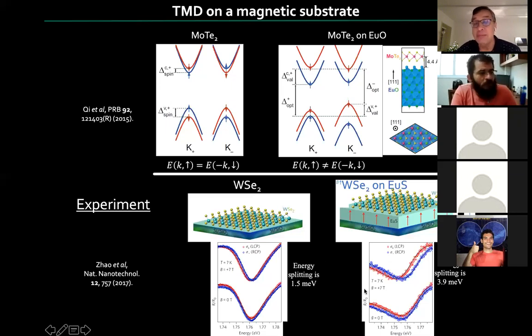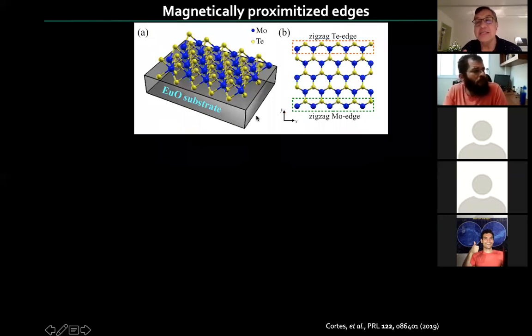And people have actually measured that, because you can measure this right and left polarization peaks and look at the circular dichroism essentially. And so you can estimate that depositing the material on something like europium sulfide is equivalent to several Tesla of magnetic field. There are no external fields, it's just a magnetization from the substrate. So we ask, what would happen to the states on the edge of a ribbon? In this case it is an edge, not an interface, for simplicity, but it would be very similar, as you can imagine.